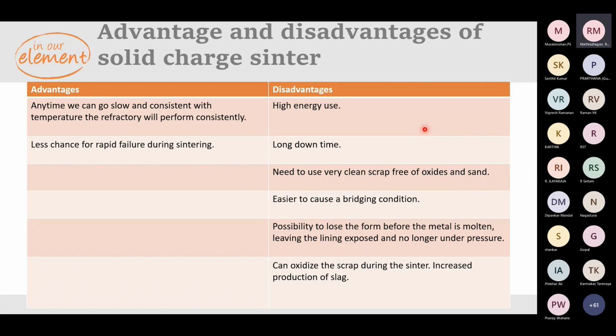So when it comes to advantages and disadvantages of solid sintering, the advantage is that you can go slow and consistent with the temperature, the refractory will perform consistently, and there are fewer chances of rapid failure during sintering. But the disadvantages are high energy use, long downtime, the need to use very clean scrap free from oxides and sand, and it is easier to cause bridging. Sometimes there's a possibility of losing the former before the molten metal is introduced, and this leads to exposure of the lining to the metal with no pressure.